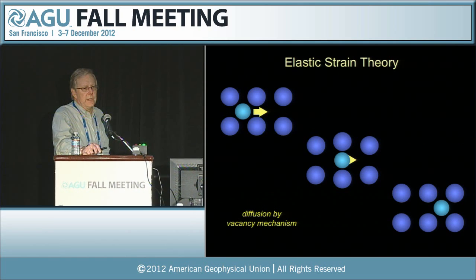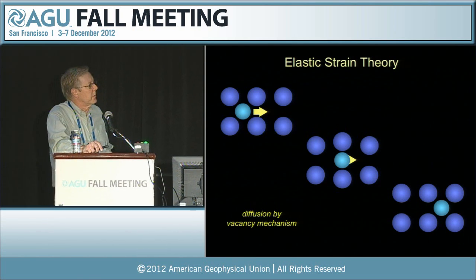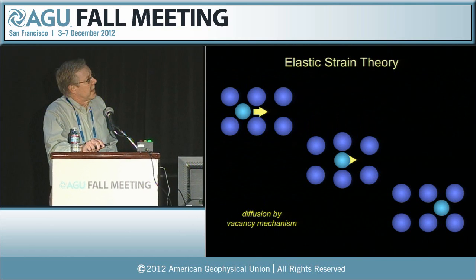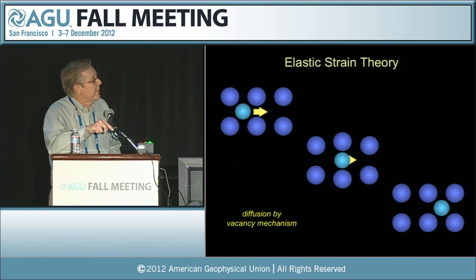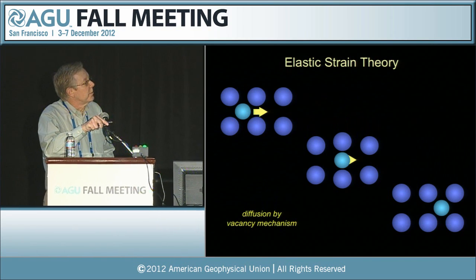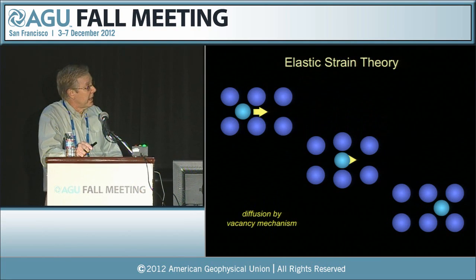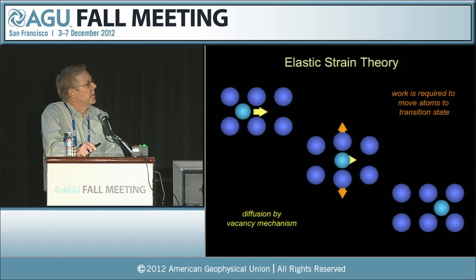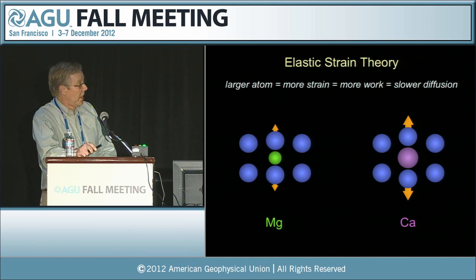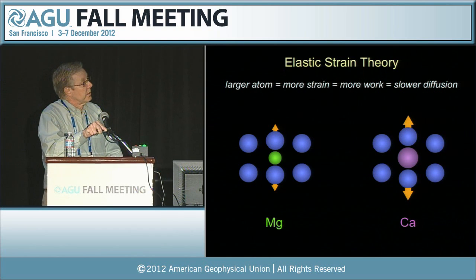Well, if we try to explain these ideas with elastic strain theory, we would start here. This is just a diagrammatic illustration of what would have to happen if we have diffusion by a vacancy mechanism. As an atom moves into an adjacent vacant site, it has to shoulder aside the atoms that form a barrier to its path, and that requires that work be done in order to reach that transition state. And elastic strain theory is very simple. The idea is that the motion of a larger atom requires more strain, which requires more work and results in slower diffusion for that larger atom.